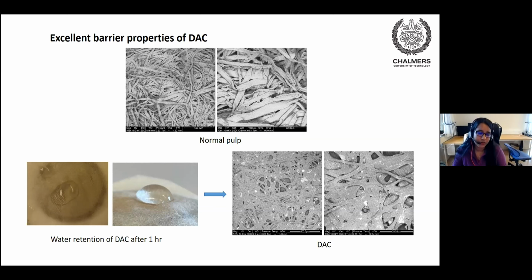You see a droplet of water on the material produced from dialdehyde cellulose, and the water does not penetrate. The photo was taken 1 hour after dropping the water droplet onto the surface of DAC. In a closer look, we see that it forms a lotus-leaf-like droplet of water, and at the bottom is the dialdehyde cellulose surface. We see that it is very hard to penetrate.